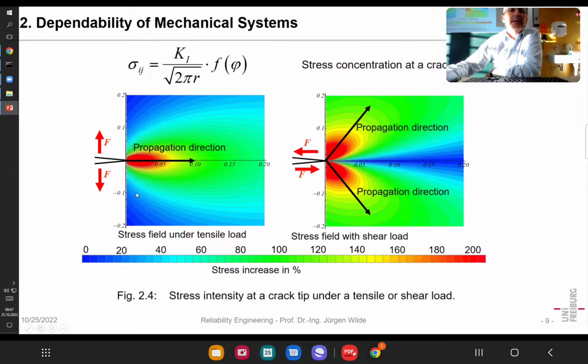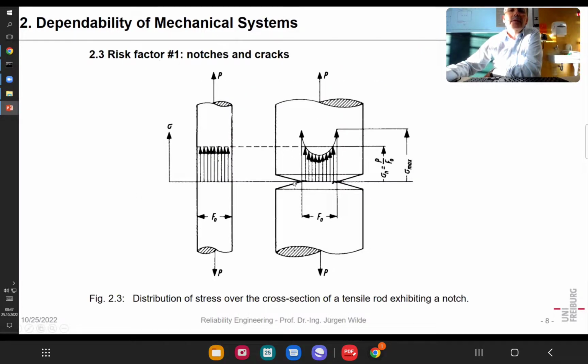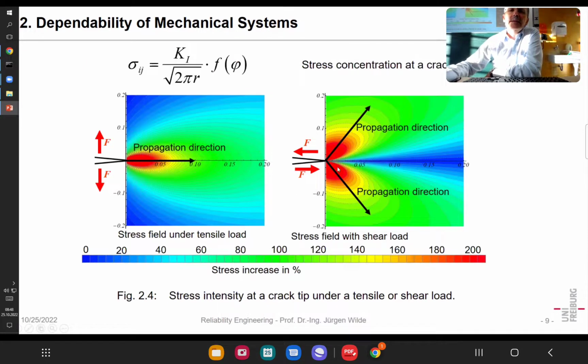Also here it makes a difference if that notch or the whole material goes more to the side, or if it's just a little to the side here. So larger is worse, you could say. Okay, that's the stress field in shear mode. And you can see in all cases, for instance here, you have stress concentrations of an increase of more than 200%. It can be significantly more, and that's the main reason why cracks or notches are dangerous.